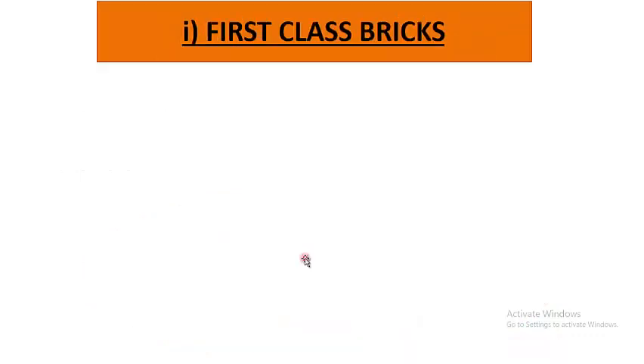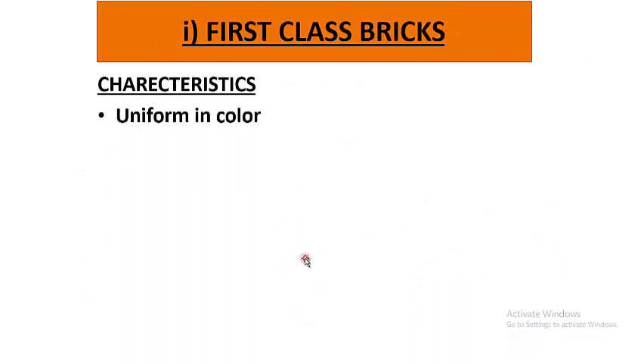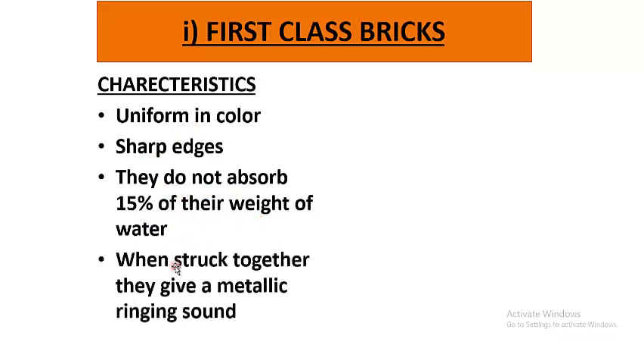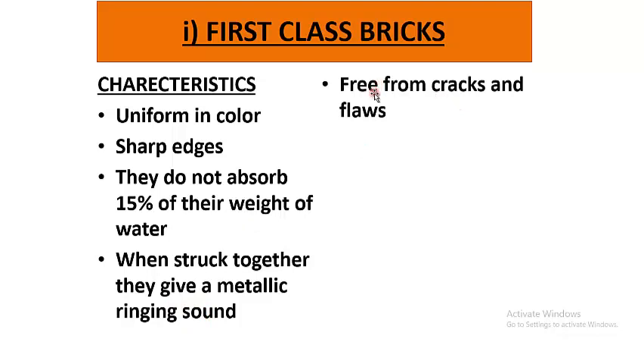First class bricks: characteristics are that they are uniform in color, having the same color throughout the brick, and their edges are sharp. First class bricks do not absorb more than 15% of their weight in water. When first class bricks are struck together, they give a metallic ringing sound. First class bricks are free from cracks and flaws.